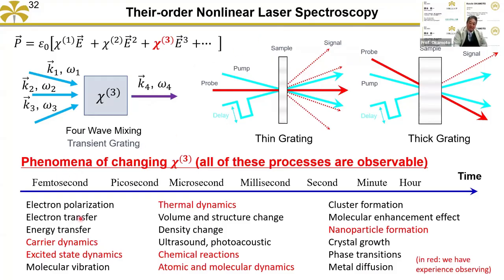And the good thing is that the refractive index is very sensitive to many processes, over many time scales. For example, in the femtosecond region, electron polarization and electron transfer change the refractive index a little. In the microsecond region, thermodynamics or molecular dynamics change the refractive index. And in the second region, clustering or nanoparticle formation changes the refractive index.